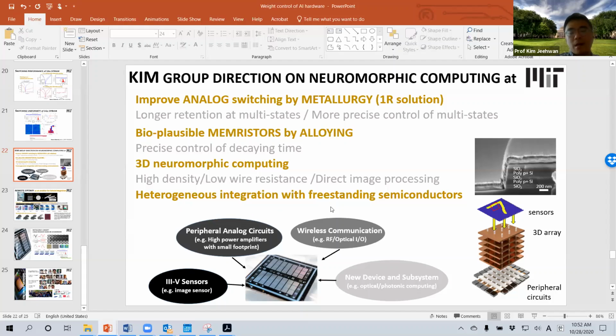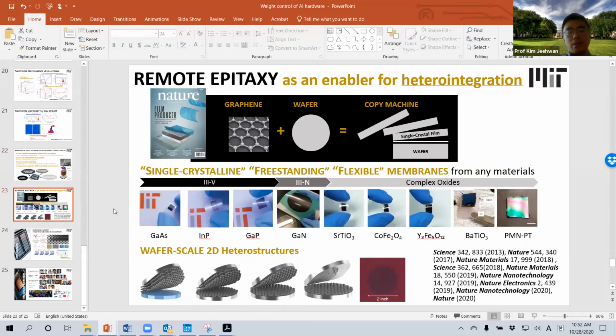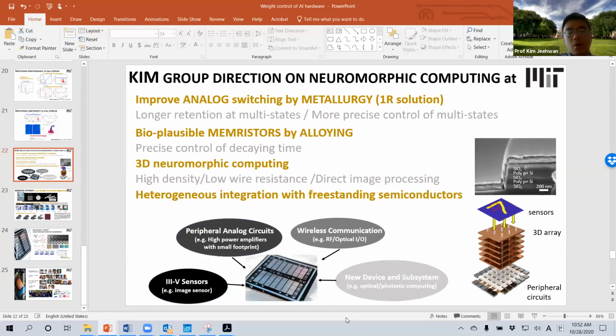At the moment, to us, it's kind of a dream, right? You put the material that you want, like a sticker. Okay, we made the basis for doing this. As you can see, all the single crystalline III-V, III-nitride and complex oxide are thin on the tape, ready to be stacked. Still, you will need to avoid some cracking and mechanical defects in the stacking process, but eventually this will enable us to heterointegrate all of them together.